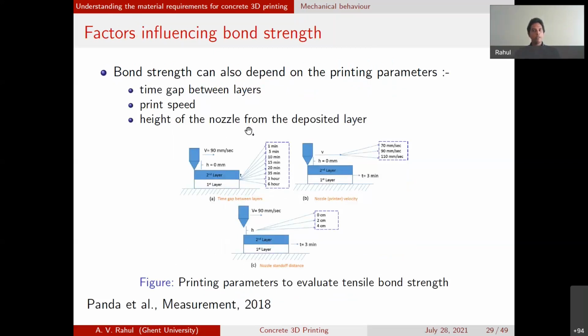One more key element that we need to keep in mind is that the bond strength can also depend on the process parameters. Say, for example, the time gap between layers. If you print with a longer time gap, it has been observed that the interlayer strength tends to decrease and the mechanical properties tend to decrease because of the larger interlayer time gap. The speed with which you're printing, if you print at larger speed, also sometimes we see that it can influence the mechanical properties. In fact, decrease the interlayer bond strength.